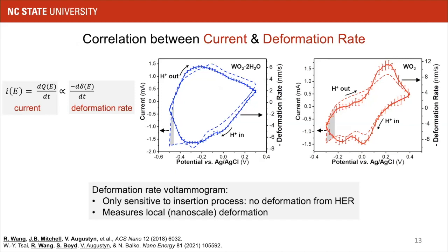Furthermore, to go back to that initial statement that I made between the deformation of a material or a molecule and its electrochemical response, we saw a direct correlation between the current and deformation rate. So if we take the derivative of the AFM data from the previous slide, we get the solid curve here with the error bars. The dashed line is the electrochemical current coming from the entire electrode.